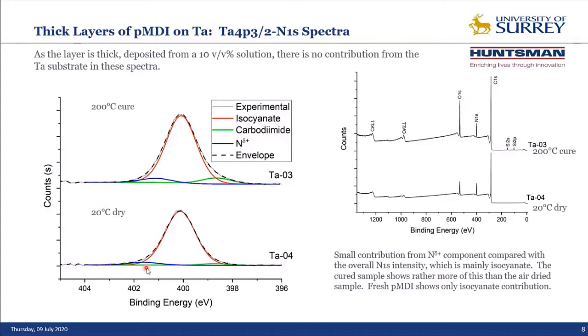If we look at the dried spectrum, we can see very little difference in terms of the energies, but the intensities are much reduced. And what we can draw from this is that any reaction product within the PMDI itself is going to be enhanced by curing at 200 degrees C. So we see a little bit by drying, a bit more by curing. So how do we explain the nitrogen delta positive? With this thick overlayer, it's clearly nothing to do with an interaction between the PMDI and the tantalum, because we're not seeing any evidence of tantalum in the spectrum.